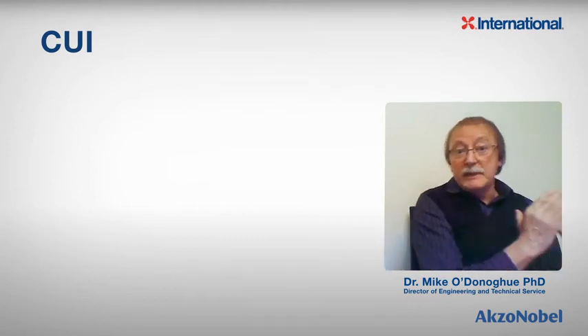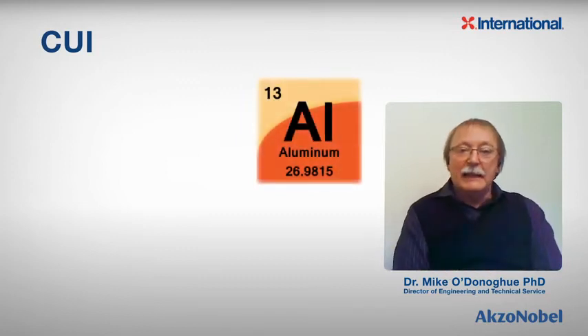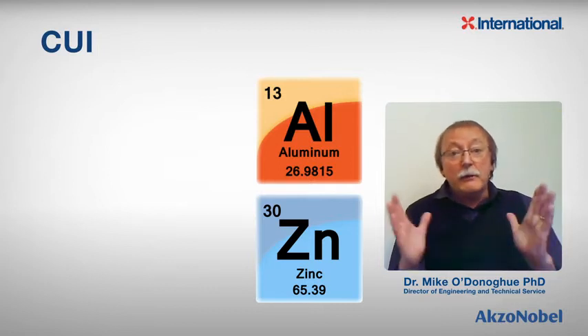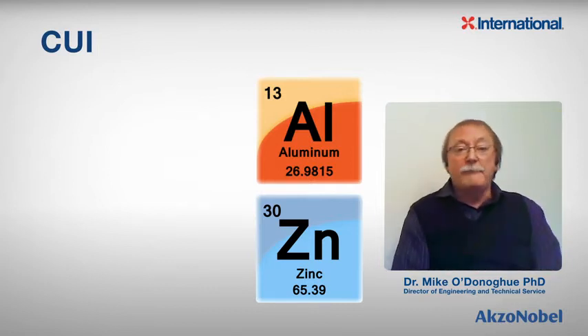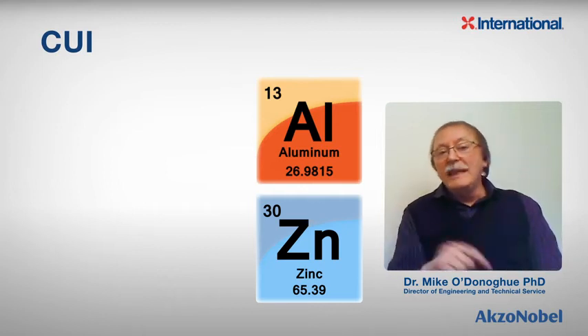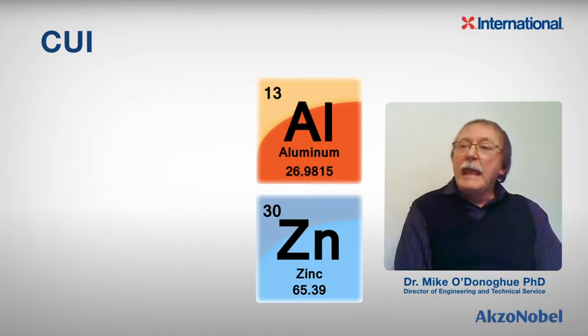But then when you start to think of aluminum, and we're going to think of aluminum from thermal spray aluminum from the technical perspective and the practical perspective. When we think of it technically, aluminum is a wonderful, wonderful metal. It loves to give up 3 electrons. Zinc only gives up 2 electrons. It's very efficient at what it does as a sacrificial galvanic anode, for example, in the offshore platforms, where it's often used, as well as bridges and dams and so on.